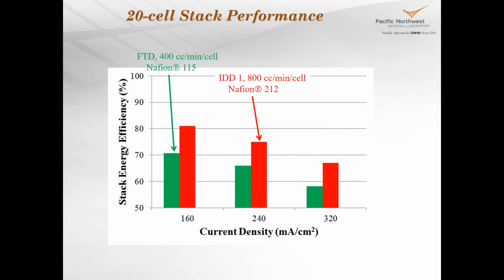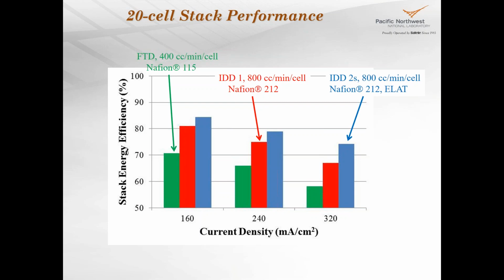And our current system is a second version design of the interdigitated flow field, and also an improvement on the electrode. You can see a further development. Right now, at 320 milliamp per centimeter square, our stack overall energy efficiency reaches somewhere around 75%, which is actually very good data.